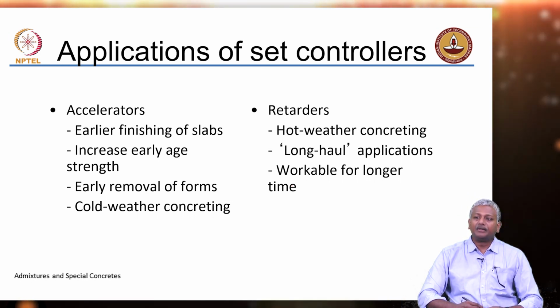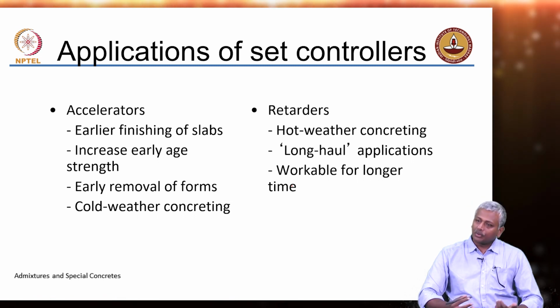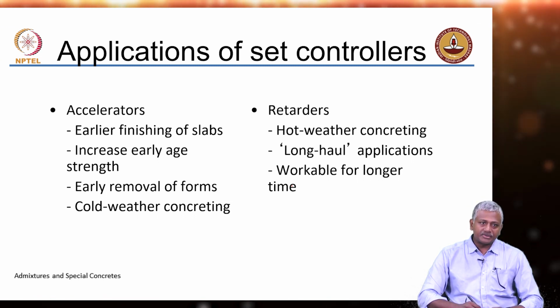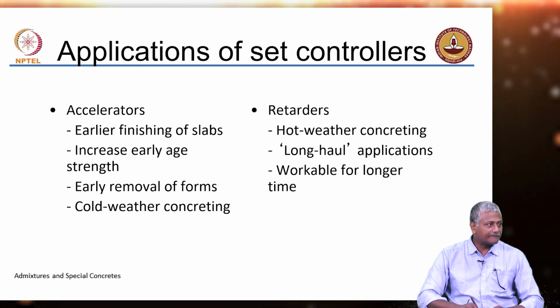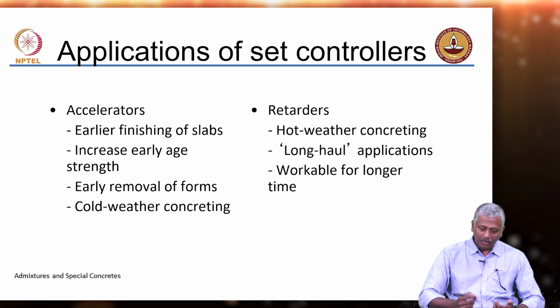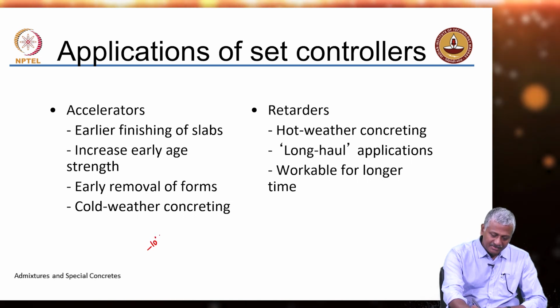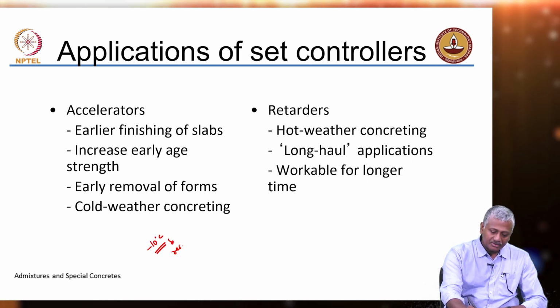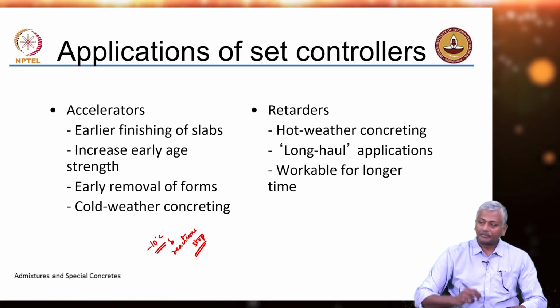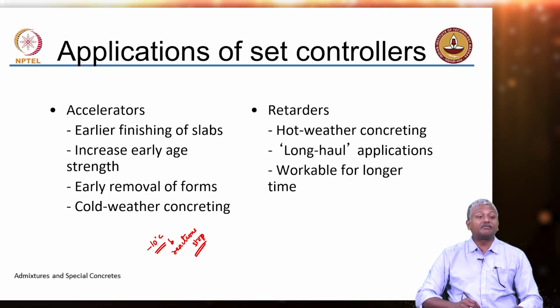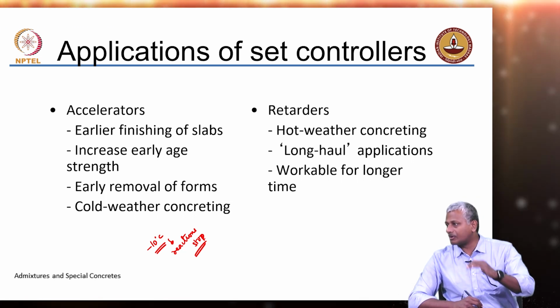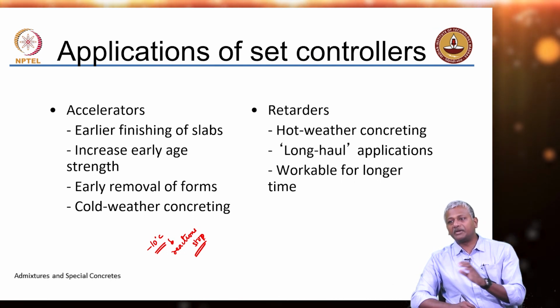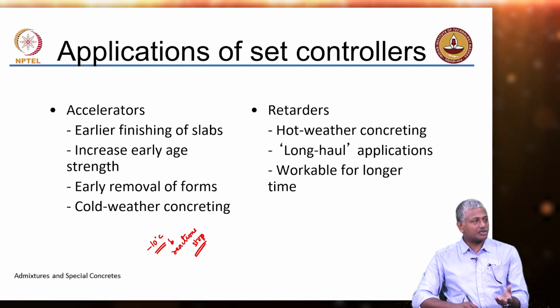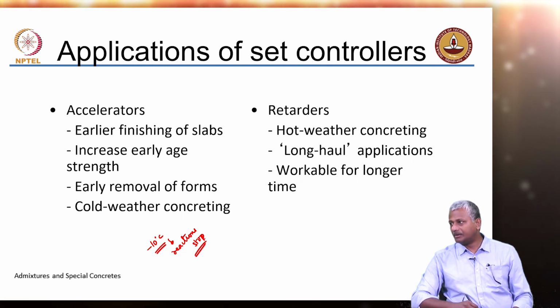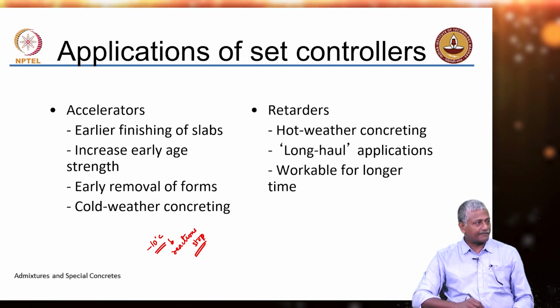Okay. Can cement reaction keep on going if you keep reducing temperatures? Yeah, at a given point, typically we say that around minus 10 degrees Celsius, the reactions may stop. Okay. So, when you are doing concreting at freezing conditions, it is very important to keep the temperature of the concrete high. Even if the ambient conditions are minus 10, you have to ensure that the water has been heated up sufficiently well to get you the required temperature, right.